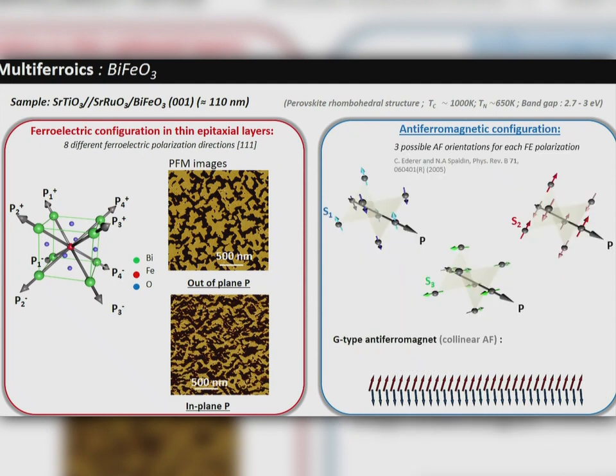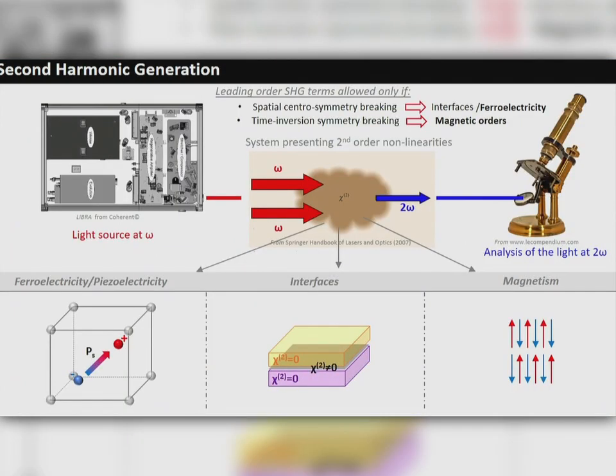And for each polarization, P polarization, you can have 3 different kinds of S domain, basically. These are the equivalent of the S domain. So altogether, that makes an interesting system because we have another level to handle the antiferromagnetic order, but it's quite a complex system. And for this, we have to choose a technique to be able to investigate it. And we have chosen, among some others, a nonlinear process, actually the lowest order, which is second harmonic generation.